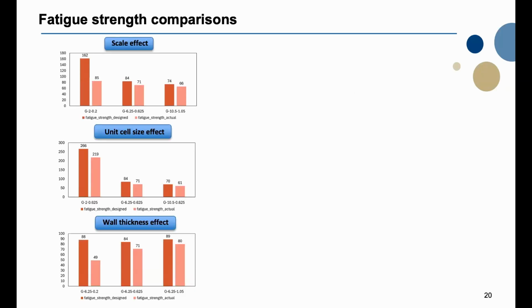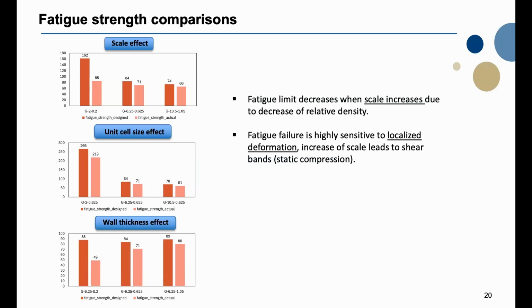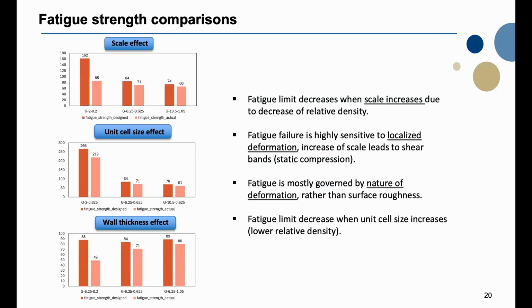And if we compare the fatigue strengths based on different categories, we can see that the fatigue limit decreases when the scale increases due to the decrease of the relative density. And the fatigue failure is highly sensitive to localized deformation. The increase of the scale leads to shear bands under quasi-static compression, and the fatigue is mostly governed by the nature of the deformation. Even in this case, surface roughness also played a role, but it's not as important as the nature of the deformation here. And the fatigue limit decreases when the unit cell size increases, as in the lower relative density.